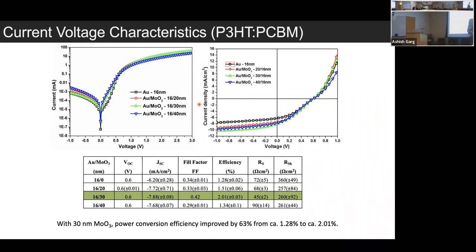The problem is that the fill factor is still not perfect. In these devices we get a fill factor of about 40%, whereas in a good organic solar cell device, you should be getting a fill factor of nearly 70% or 75%. That's mainly because, one, the resistivity of the components is high. Because you are using metal oxide on top, the resistivity is still high. As a result, your series resistance is high, and the shunts are also high because the aluminum is not a perfect electrode. It does provide problems with the bottom side in zinc oxide, leading to more recombination.